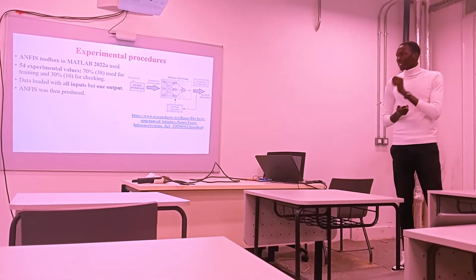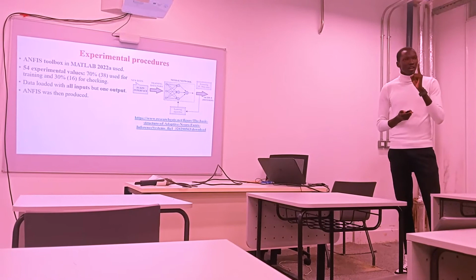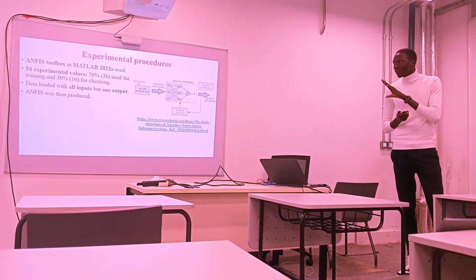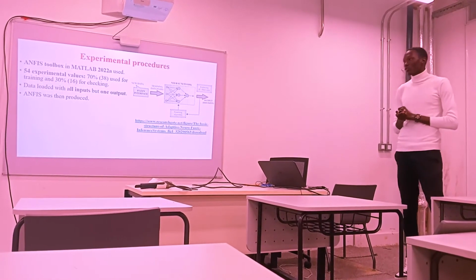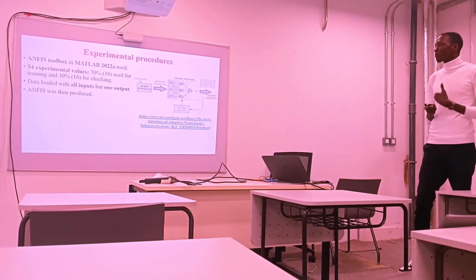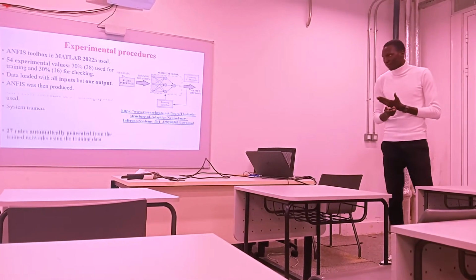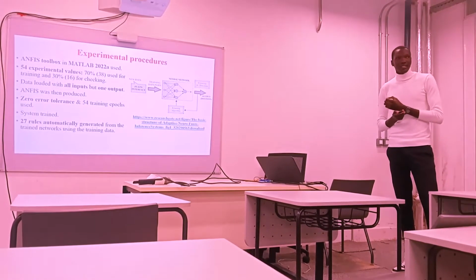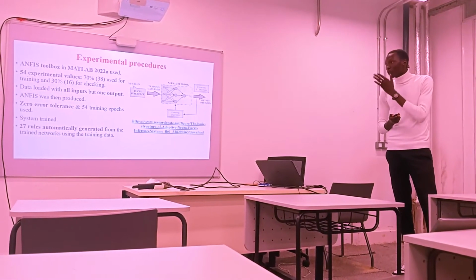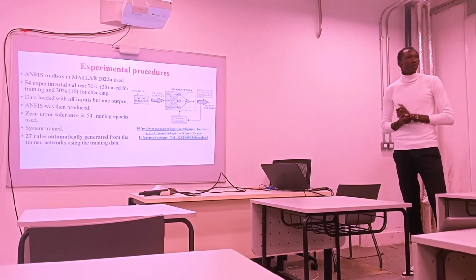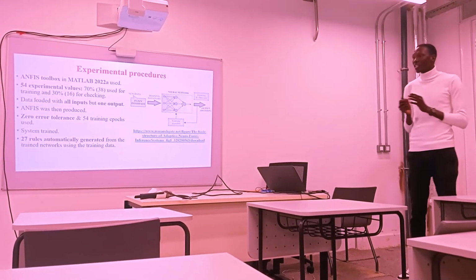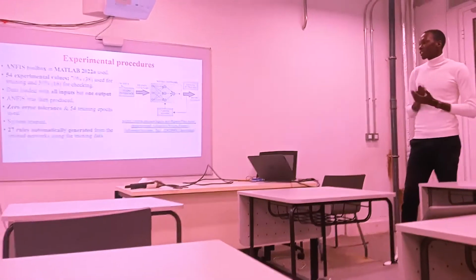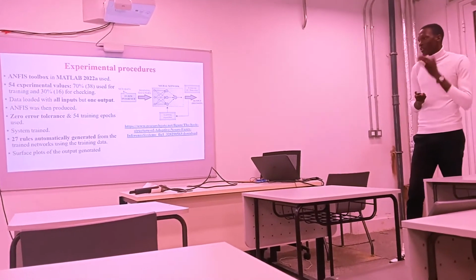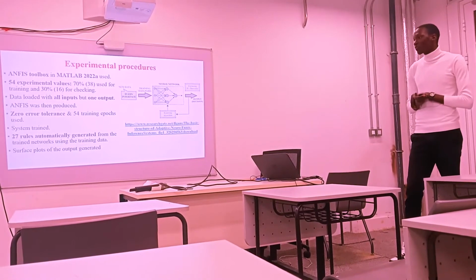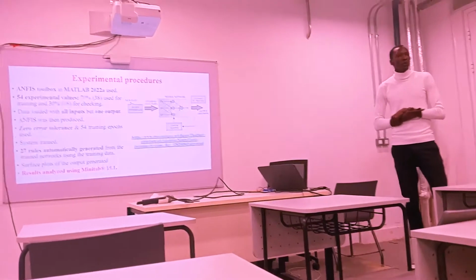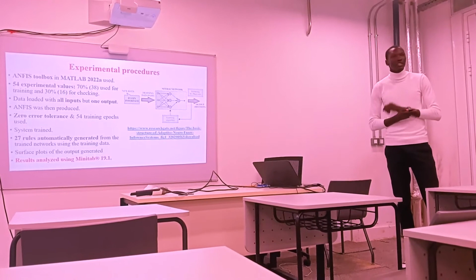And then we loaded the data with all the inputs, but only one output at a time, because ANFIS does not accept more than one output. And then we produced the ANFIS, the system. We set the tolerance to 0, and 54 training epochs were used. Then we trained the system, and we generated 27 rules automatically from the training networks using the training data. And then we produced the surface plots of the outputs. And then we used Minitab 19.1 to analyze the results.